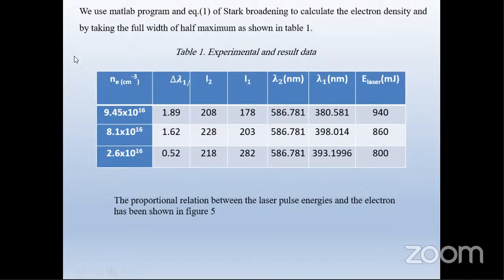This is NE, as you see, NE in centimeter cubed minus 3, and delta lambda, I2 and I1 the intensity 1 and the intensity 2, lambda 2 and lambda 1 in nanometer, and also finally the laser energy pulse in millijoule. The proportional relation between the laser pulse energy and the electron density is shown in figure 5.